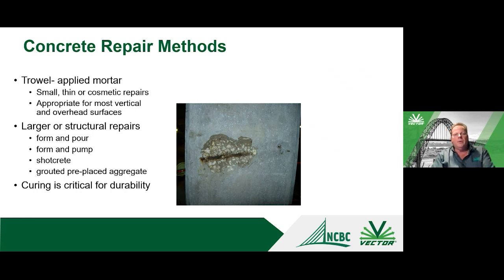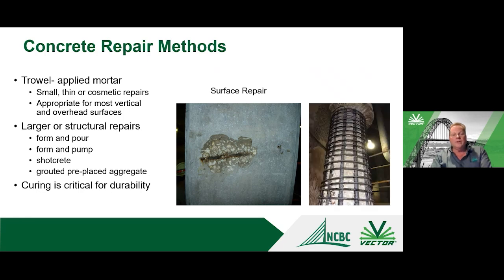Different types of repair materials. We have your trowel applied repair. They're usually more for vertical repairs that are maybe smaller or somewhat cosmetic in nature. When you get into larger, more substantial repairs, you may just go with a quality concrete mix: form and pour repairs, shotcrete repairs, etc. I would say those would be more structural in nature. But whatever you do, these are cement-based materials, mostly Portland cement-based, and we can't forget the importance of curing. Curing is for durability. If we want to keep the repair material durable, we want to keep it crack-free. So curing, to allow the strength development of the material, is really critical.